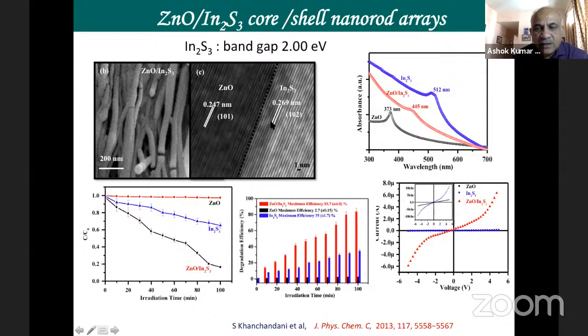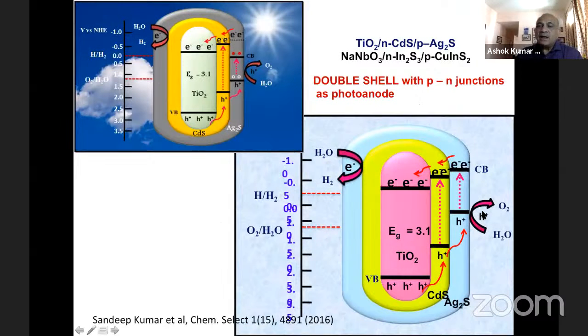This is the high resolution electron micrograph showing the two at the interface. On one side you have zinc oxide and then you have indium sulfide, and the efficiency goes up in the photocurrent and also in photocatalysis. If you want to degrade a dye, you can see the dye gets degraded much faster when you have the core-shell structure. So it is much more effective in degrading the dye, and it gives a higher current. Now, this is another design where we are using two shell materials.